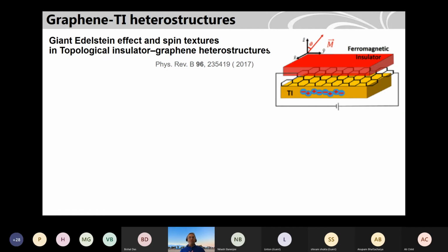Okay, so you have to break the symmetry to go into this anomalous Hall effect. But if we consider spintronic applications, if you have a magnet and a TI and you bring them together, then you can break the symmetry. Then the interface quality is not the same. So there are proposals on how to get rid of that problem by putting a graphene in between.